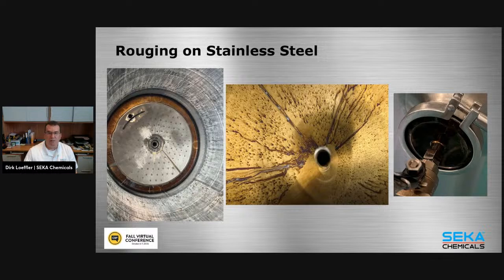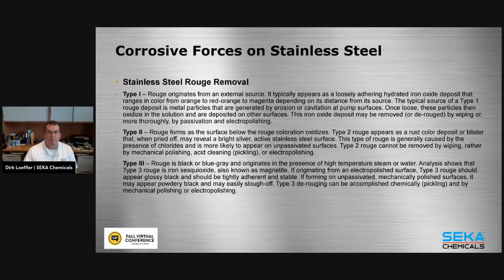So again, generally all these things have a failure of the underlying passivation, generally high chloride content in the water or coming in through certain chemicals, and actually oxygen. So if you use an oxidizer, for example, with your caustic, peroxide based, and your stainless steel is not passivated, and the stainless steel is bad quality. So a lot of things sometimes have to come together that would normally not affect a tank or a piece of equipment. But if all these factors come together, then you end up with something like this.